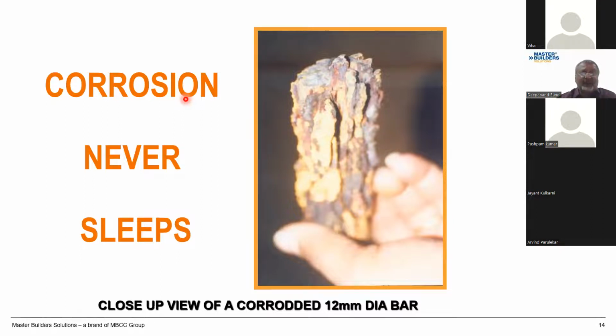Now, this is actually a 12 mm dia bar that I picked up from a water storage tank years back when I had visited MJP in Thana. It was the last stage where you dose chlorine gas into the water for the purification process. And that's where the fumes of the chloride hit the soffit of the tank, and probably it was not protected well, or the cover was too low, a very old construction. But when I measured this reinforcement bar in the lab, it was about 52 millimeters. Now you can imagine, over here itself, I see about 400% of expansion that has happened.